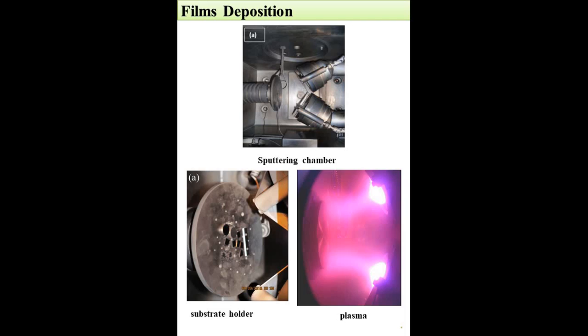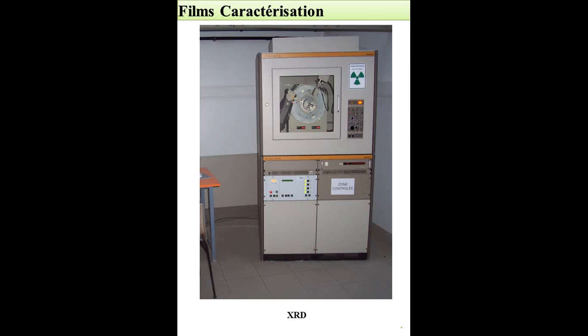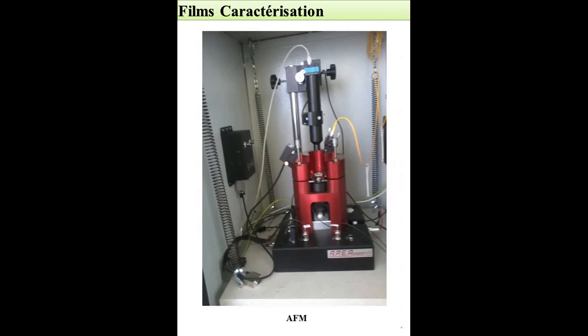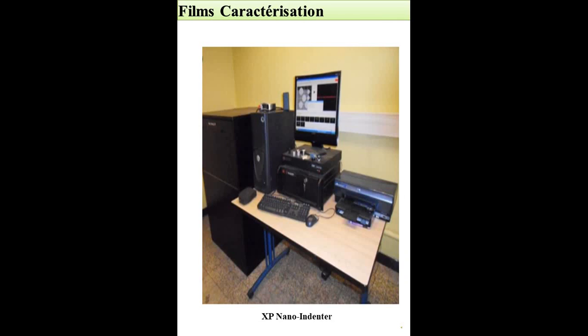Zirconium nitride thin films were synthesized using radiofrequency reactive magnetron sputtering on XC100 steel substrates at different nitrogen flow rates. The crystalline structure, morphology, and mechanical properties of the produced films as a function of nitrogen content were characterized by X-ray diffraction, SEM and EDS, AFM, and nano-indentation.